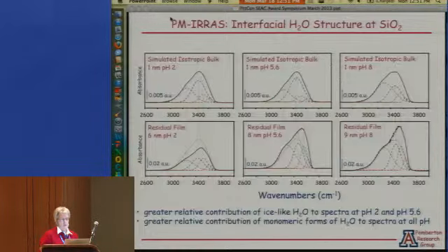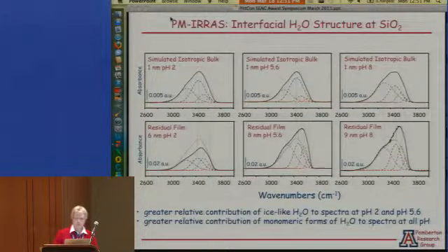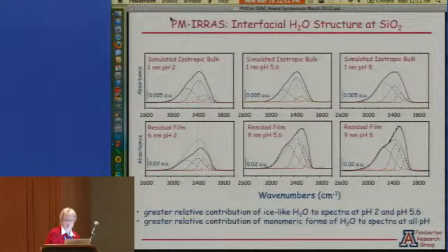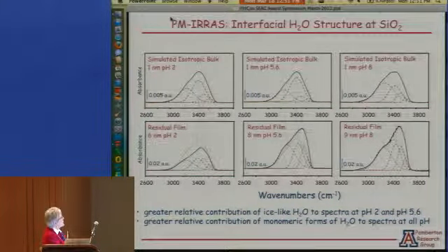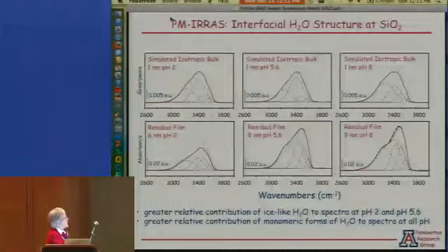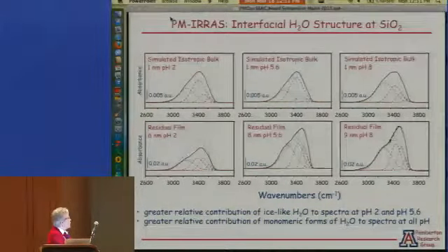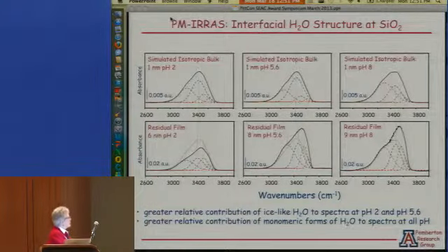So, as I said, of course, our real interest in this was to get spectroscopy information about molecular structure in these interfaces. I can't finish without showing a little bit of that, and so this is some infrared reflectance absorbance data that we got actually for these water layers at silica. And the top spectra are what the isotropic bulk spectra look like, and then the spectra below for these three different pHs shows you the spectra in the OH region for the emersed layer, the residual films.